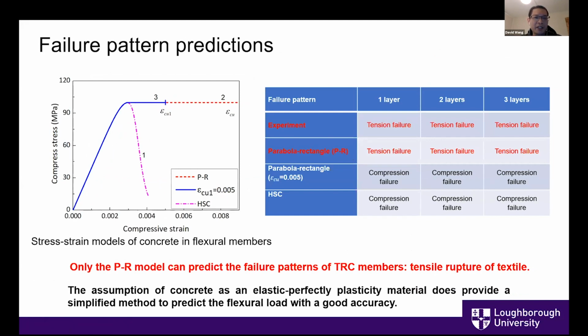We also did some failure pattern predictions, and we can see that if we use different concrete models, our prediction will give very different failure modes. If we use the parabola rectangular model with the ultimate axial strain of 0.01, which is curve 2, we are able to predict that concrete beams will fail under tension. But if we use curves 1 and 3, as we can see from the left figure, the prediction tells us the samples will fail in compression. So the assumption of the concrete as an elastic, perfectly plastic material does provide a simplified method to predict the flexural load of printed concrete samples with good accuracy.